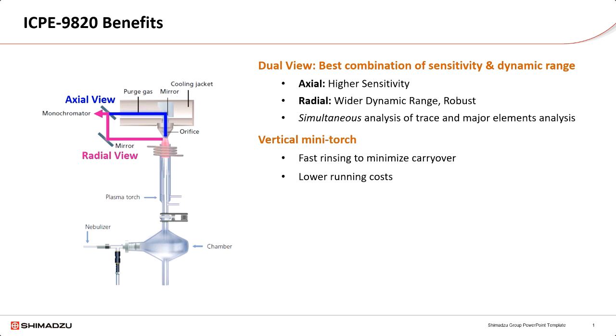The torch in Shimadzu ICPE-9820 is placed vertically. This enables fast rinsing of the sample introduction system to minimize carryover. Running ICP-OES is very expensive due to the high consumption of argon. A regular-size argon tank can only last for about a day. Shimadzu adopts a mini torch that has a smaller diameter. The mini torch uses less argon. It only uses about 2/3 of the argon of a conventional torch, saving operating cost in the long run.